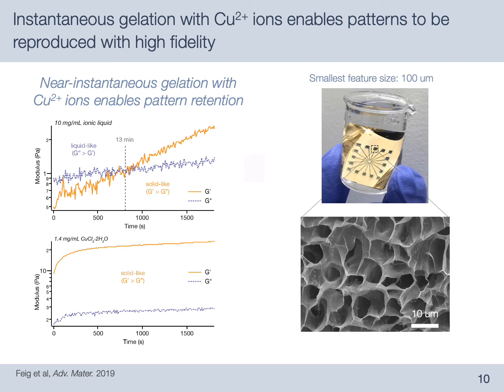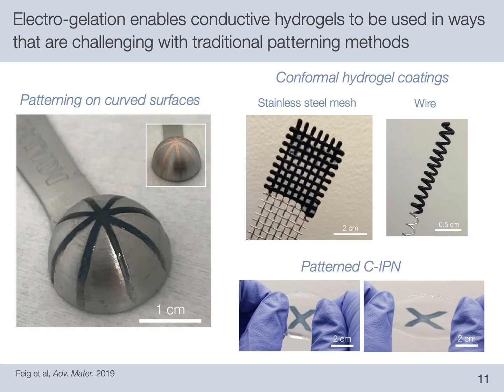Therefore, we're able to use electrogelation to pattern PEDOT:PSS hydrogels into fine feature sizes down to 100 microns, while maintaining the favorable porosity of the hydrogel. Moreover, because electrogelation initiates gelation at the substrate surface, we can easily use this method to pattern onto curved surfaces or to generate conformal hydrogel coatings onto arbitrary three-dimensional structures.